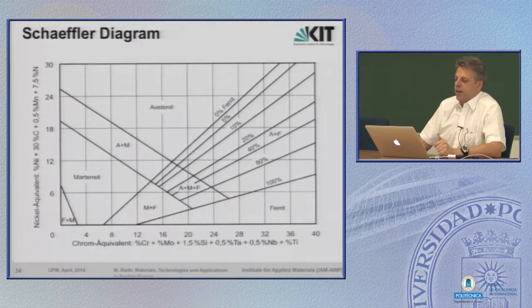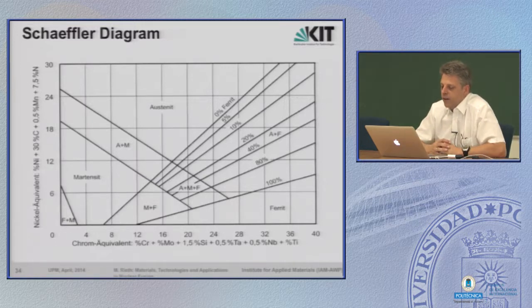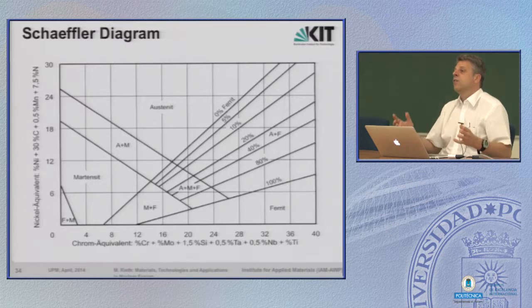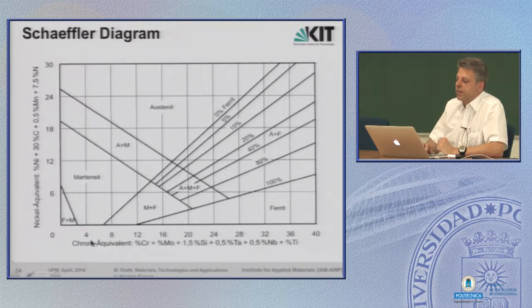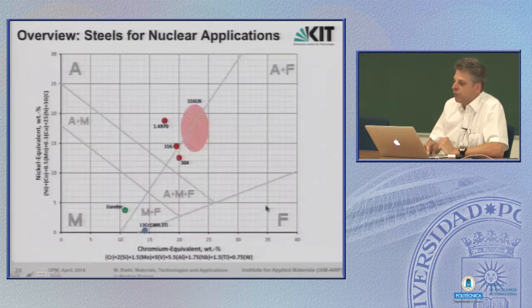I think we can skip that. There is another diagram which gives you approximately a recipe of how to produce steels of different kinds. You have here the amount of ferrite formers, that's called chromium equivalent, and the amount of austenite formers, that's the nickel equivalent. You calculate it with this formula, end up at a point, and this point gives you the structure of your steel. It could be martensitic, austenitic, ferritic, or some mixture of phases.